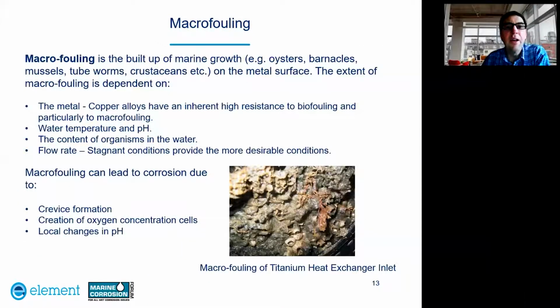If we now look at macrofouling, so macrofouling is the build-up of marine growth, which can be oysters, barnacles, etc., on the metal surface. So the extent of macrofouling is dependent firstly on the metal. So copper alloys are widely used in marine environments because they have an inherent high resistance to biofouling and particularly to macrofouling. So the other factors to consider are the water temperature and the pH, the content of organisms in the water, and also the flow rate.